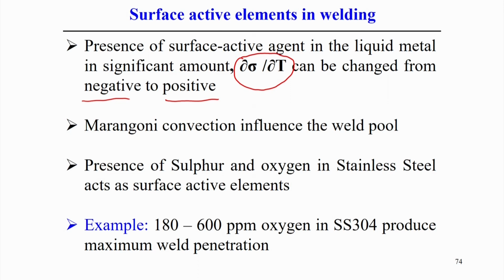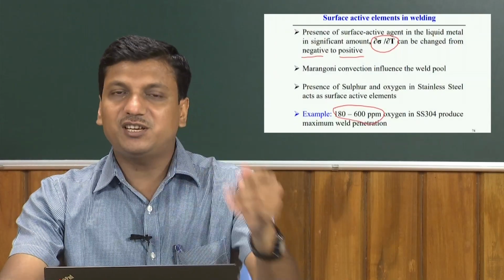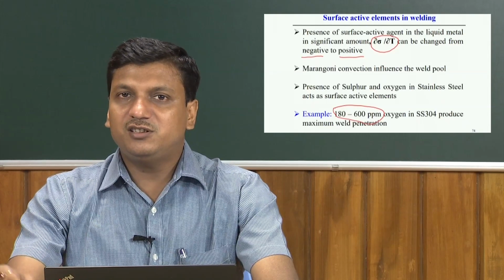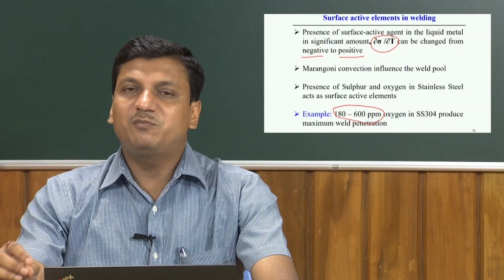So, that means there may be some optimum amount of the surface active elements at which we can achieve the maximum weld penetration. But if we further increase the amount of the surface active elements, it does not influence penetration in this case. So, we cannot increase penetration too much by abruptly increasing the amount of surface active elements, but at the same time a very small quantity of the surface active elements may also not be beneficial to increase the depth of penetration. So, this optimum amount is practically observed to give the maximum penetration. So, the conclusion is that some optimum quantity of the surface active elements is always beneficial to get the maximum depth of penetration in case of any welding process.